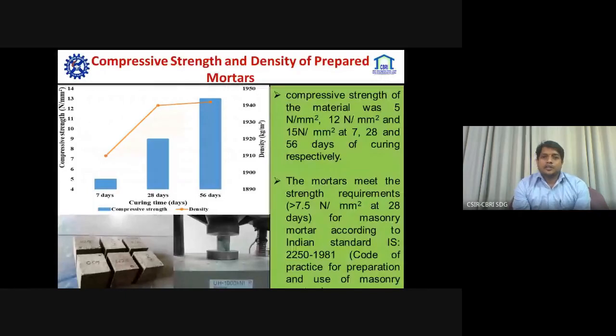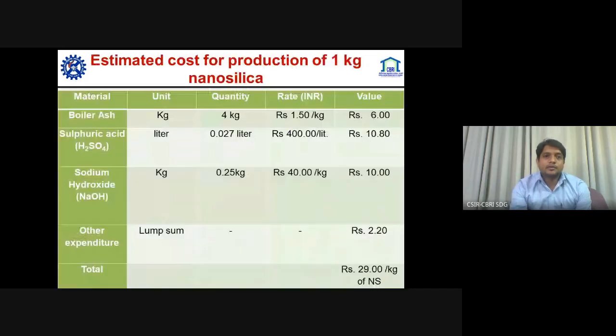The compressive strength and density of prepared binder, it was clear that compressive strength of the material was 5 Newton per millimeter square and 12 Newton per millimeter square and 15 Newton per millimeter square at 7, 28 and 56 days of curing respectively. The mortar met the strength requirement at 28 days for masonry mortar according to Indian standard 2250. The estimated cost for production of 1 kg nanosilica was around 29 per kg of nanosilica on the basis of chemicals required and ash required.